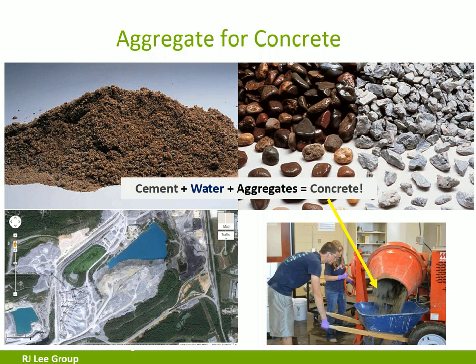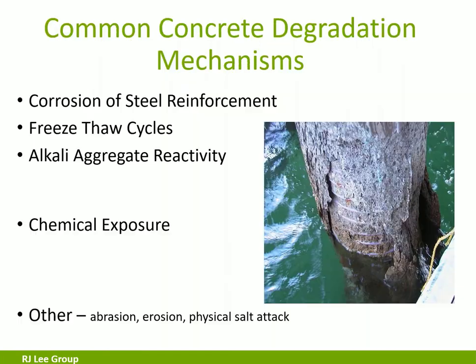The aggregate comprises about 70% of the hardened concrete by volume, and they're more than just fillers in concrete. The aggregate properties greatly influence concrete performance and strength. Qualities of the aggregate can affect the ability of the fresh concrete to be properly mixed and placed, which then can affect the hardened properties and the durability. Many of the negative qualities and properties will be flushed out with preparation and testing to meet the requirements for concrete following ASTM C33. And in addition to specifications that are specific to the application, which may include some additional testing and validation of quality.